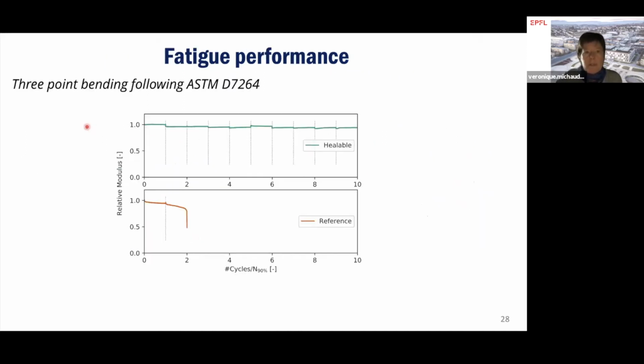So what we found in that case is that if we look at the bottom, which is the reference material, we cycle it up to 90% survival. Then we put it in the oven, we put it back, we cycle again, and it started to fail after twice the number of cycles that we had done.